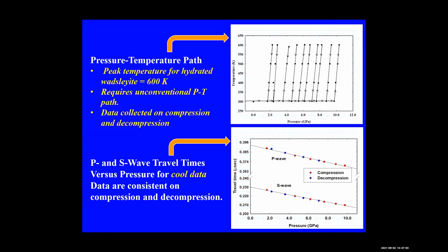The bottom figure shows a plot of the travel time of P and S wave for the sample, for the data collected at the end of each of the cooling cycle. Compression and decompression travel time, shown in red and blue respectively, are consistent for both P and S wave, and both data sets decrease systematically with pressure. We increase the precision of determining the pressure dependence of the acoustic wave velocity by having this many data points in the analysis.